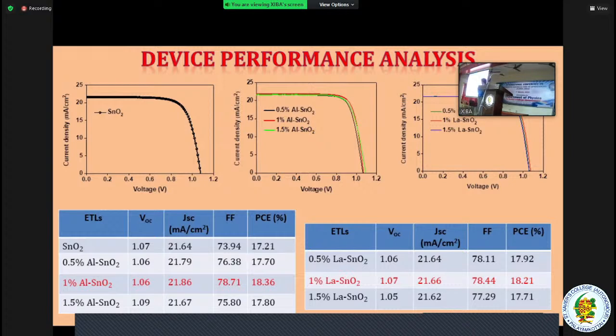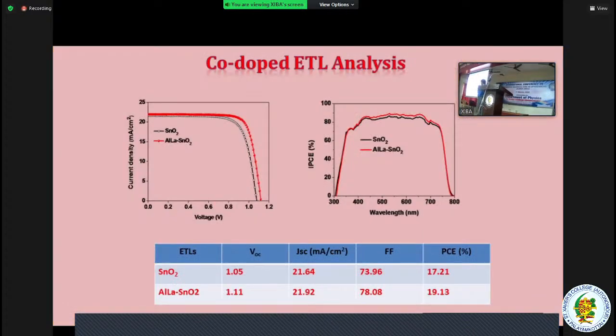Next. So this is for aluminum lanthanum doped tin oxide. Here you see for the pure tin oxide, the PCE value is 17.21, whereas the aluminum lanthanum doped tin oxide gave us 19.13%. So this is a very, very important result. You can ask me, what's the difference with only this percentage? How does the 2% make a great impact? But even if you change the conversion efficiency by 0.1%, that is a really good result. So in our case, we got nearly 2% more with aluminum lanthanum doped tin oxide as an ETL layer. Next.